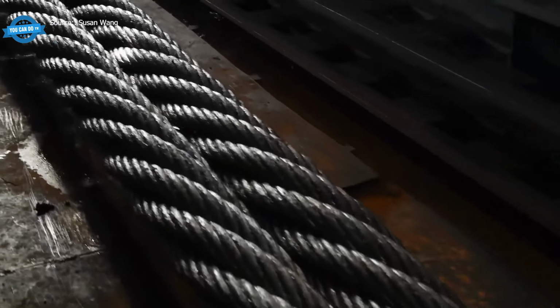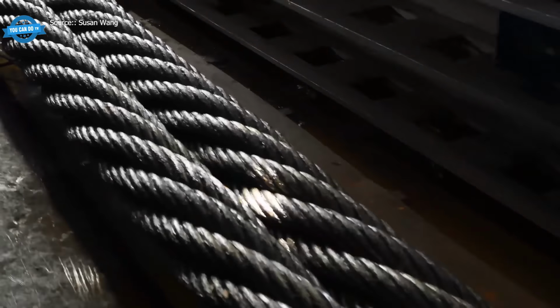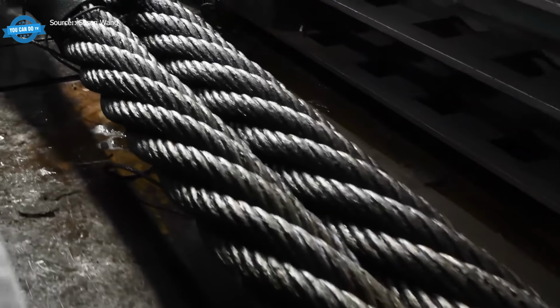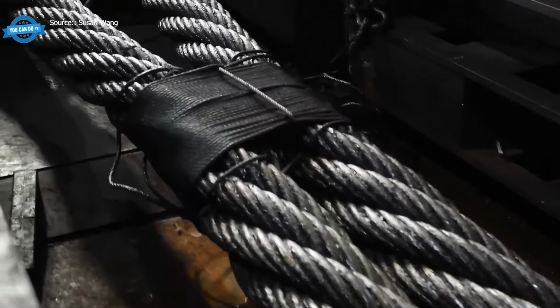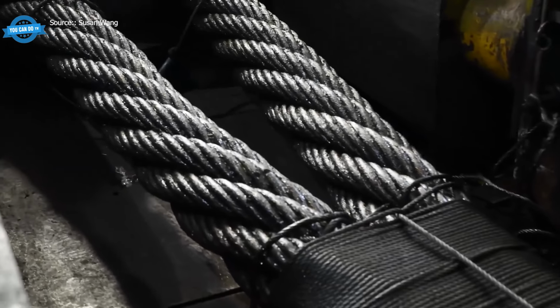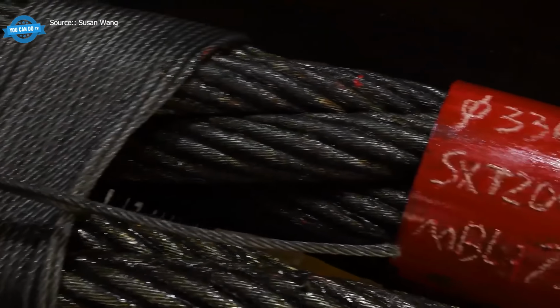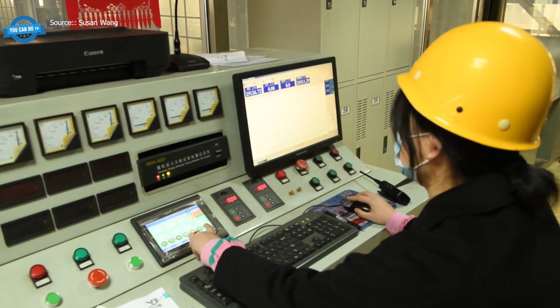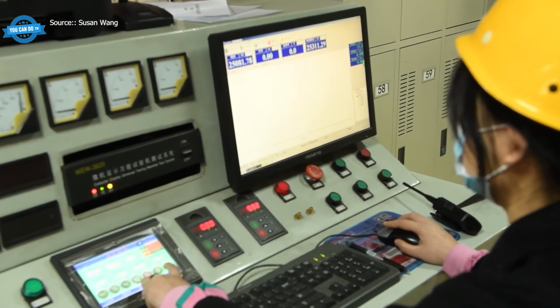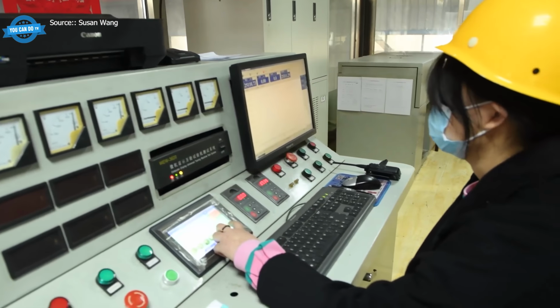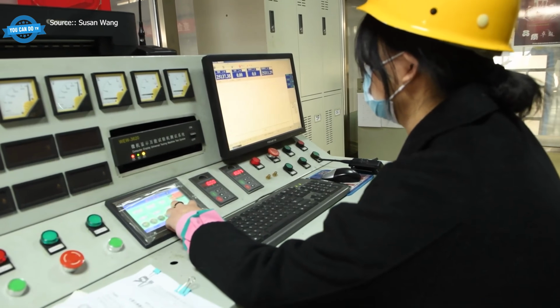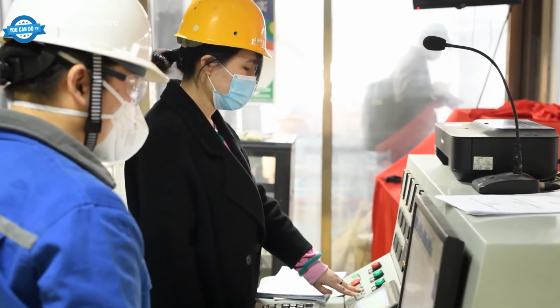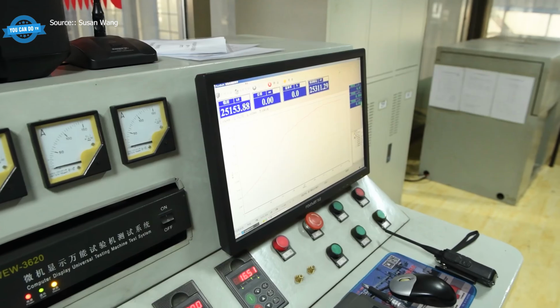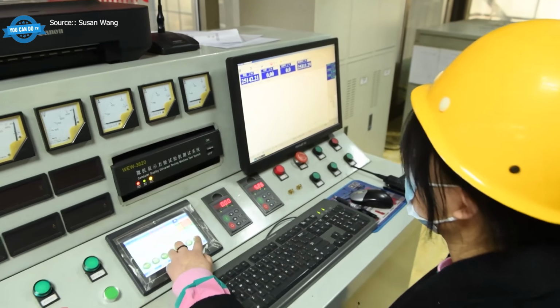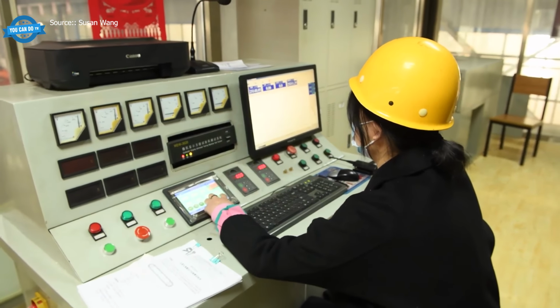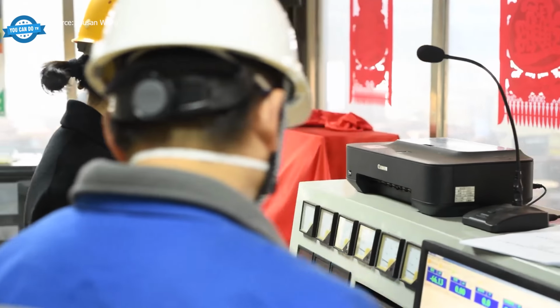The rope goes into a hydraulic testing rig the size of a small warehouse. Cables get tensioned to the certified working load, then to twice that, then to the point where the manufacturer would rather look away. At the control panel, an operator watches the load build while the rope is tested. Pass the test, and it is marked and cleared for delivery. If it does not hold, the certificate does not get stamped, and the manufacturer gets a very expensive conversation instead.